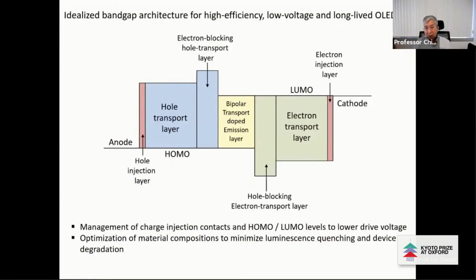So today, this is the classic structure that everybody is trying to aim at or accomplish, and that is a 5-layer structure, 7 altogether, in fact, including the injection layers. The injection layer is to provide the ohmic contact in both cases. The transport layer is to provide, of course, the transport of the charges. So these can be doped layers, electrically doped, we call it, to increase the conductivity. So this can be the doped conductors, by Novaled and companies.